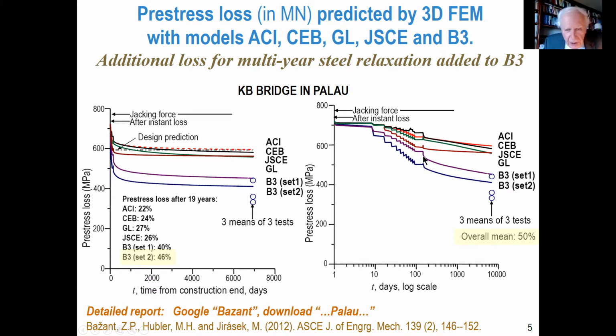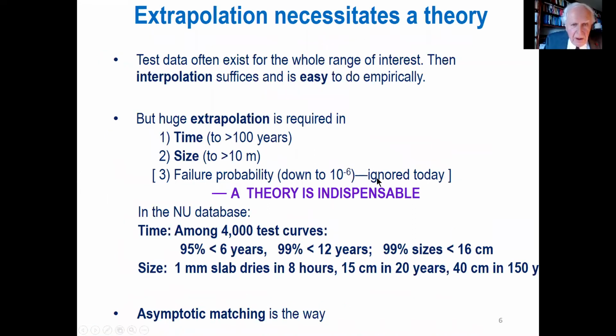This is the same in logarithmic scale, and this has its source, of course, in creep of concrete, but also, and that I will not be able to discuss, in relaxation of steel over decades, which surely happens because of viscoplasticity. It cannot be explained by creep of concrete only. So the main problem is that we need to extrapolate. The extrapolation is huge.